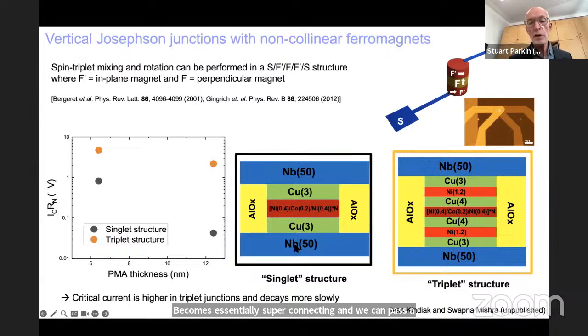However, that ferromagnetic layer will quench the superconductivity. So now we can measure that by the critical current at which the superconductivity is suppressed. And this critical current, shown in the black, the singlet structure shown like this, will decrease quickly with the thickness of that perpendicularly magnetized structure shown on the left-hand side. On the right-hand side, shown in orange, is what we call a triplet structure, in which we add more magnetic material, in this case, in-plane magnetized nickel. So it's thicker, 1.2 nanometers, so that's now in plane.